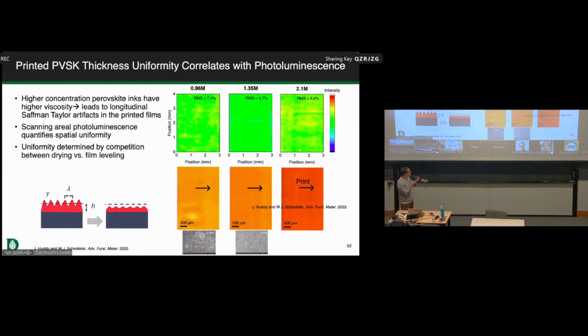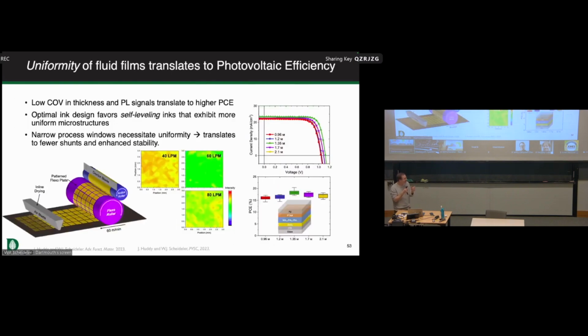And what we find is that there's actually this deeper correlation also between the fluid film thickness and the optoelectronic properties. So maybe this was obvious, but it certainly was a surprise to us when we found these images, that the photoluminescence and the other optoelectronic properties would essentially give us the same kind of image that you'd get from variations in the thickness. So it's telling us that if you want to make good solar cells, you really have to print it perfectly. You have to go essentially to a length scale or a uniformity scale that you could never achieve before with typical graphic arts printing. And that's essentially at the single nanometer scale for the variation.